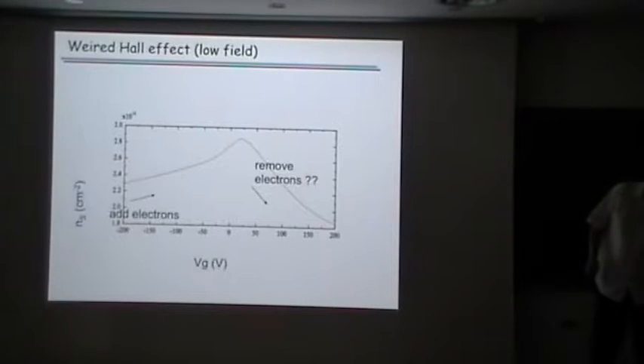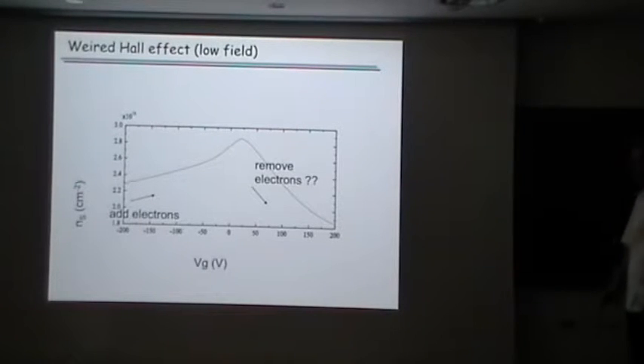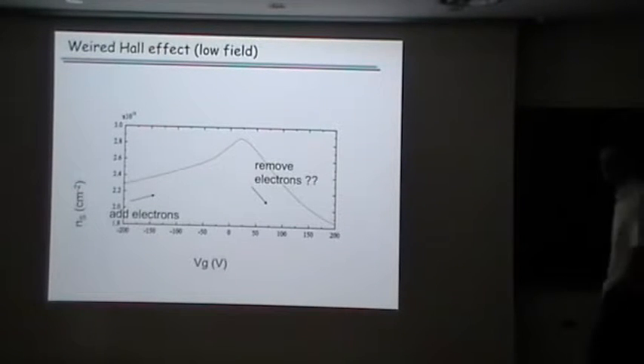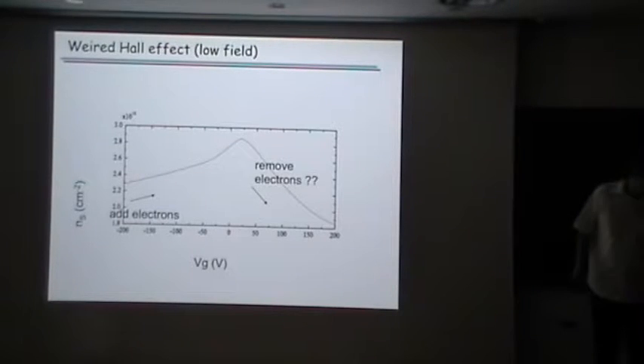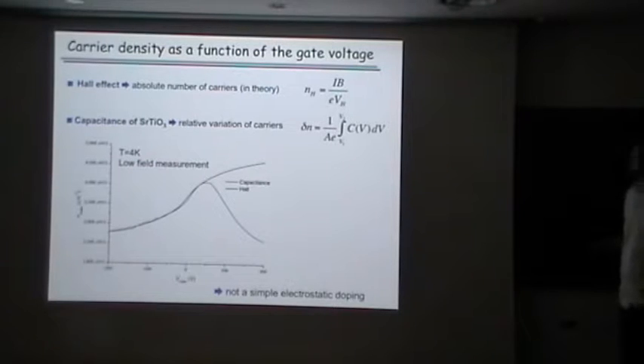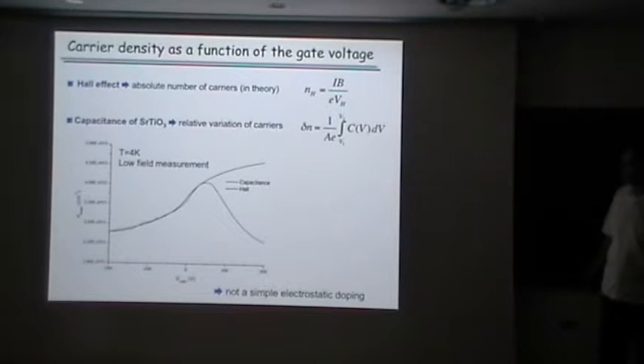Okay? Now, if we measure the Hall effect, to know the number of carriers, that's kind of strange because when we are going this way with the gate, so of course this is 0, here we add electrons, so of course the number of electrons is increasing, but then at this very same point, like around 0, it goes down. But you are still putting electrons in the system with the capacitor. And if now we measure the capacitance of the system and just integrate, of course we don't have the absolute value, but you see, this curvature is exactly the same for the Hall number of carriers and for the capacitor. So we can just adjust the absolute value here, and you see it's a perfect fit. And therefore here we're still adding electrons, but of course the Hall effect at low field is going down.